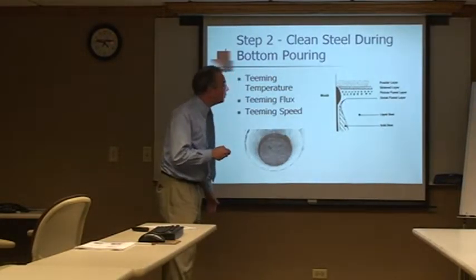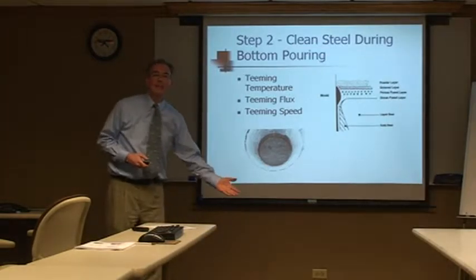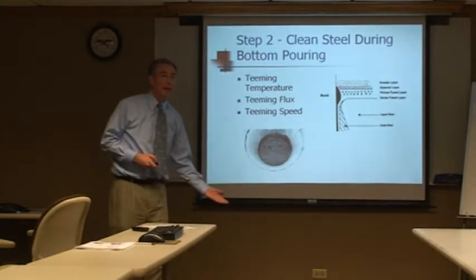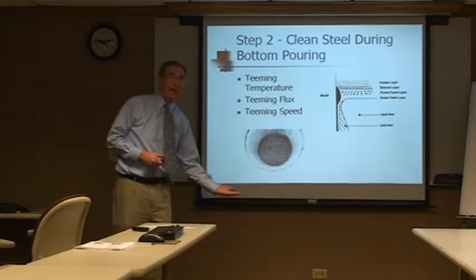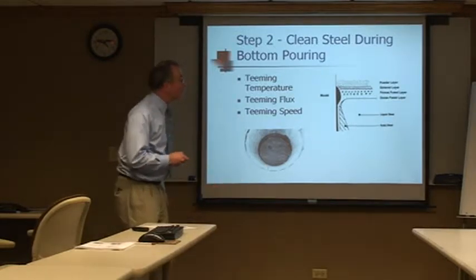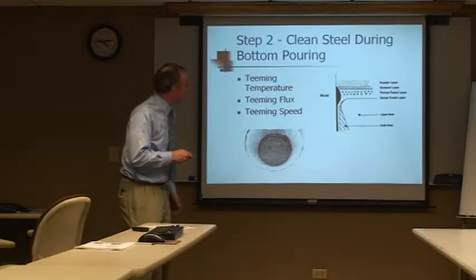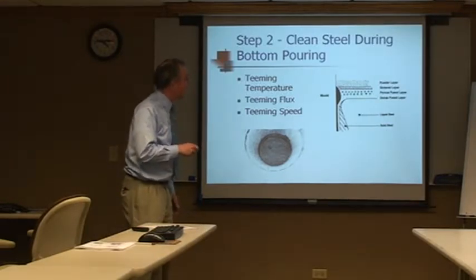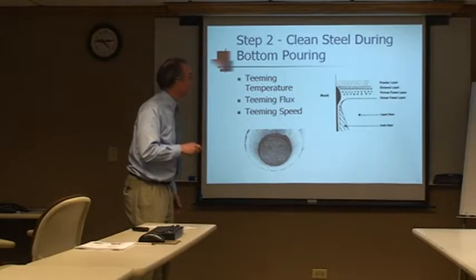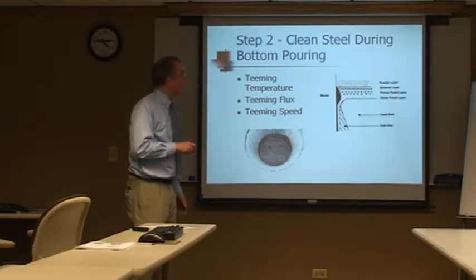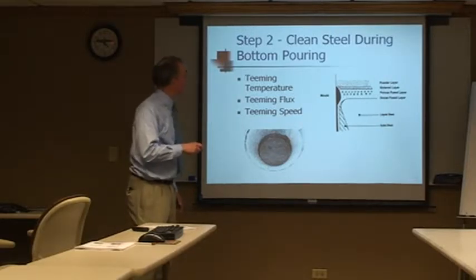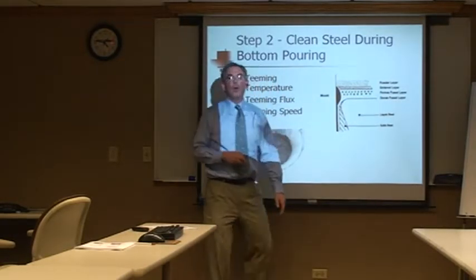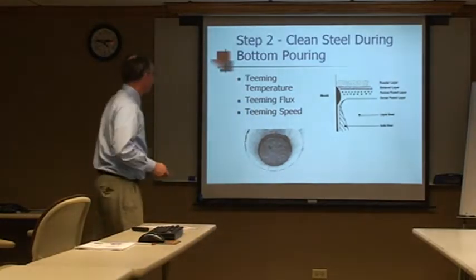Because if we start to pour too fast, and a standard rule of thumb is 6 inches per minute rate of rise. So 6 inches, I won't waste a minute here, but that's not very fast. But if you start pouring faster, it's going to start becoming turbulent. And then when it starts becoming turbulent, now this is getting disturbed, and now this flux is starting to mix with the liquid steel. And now we're playing with fire. Because maybe this can float back out, maybe it can't. If we're pouring too fast, we can risk entrapping teeming flux.